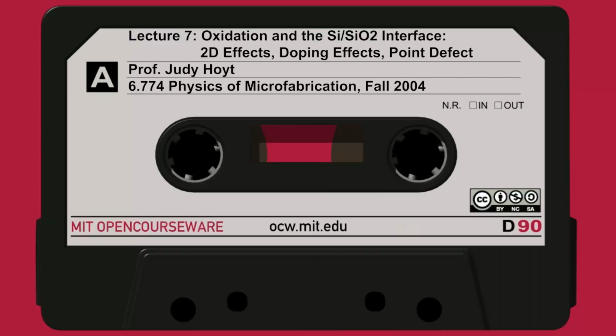But look at the boron. The junction depth for the boron is much deeper here. You can get the junction depth, say, from the region between the green contour and the blue. The junction depth is a lot deeper underneath the place where the oxide grew. So this tells us right away that we are getting oxidation-enhanced diffusion of that boron. And this is something that's been simulated.